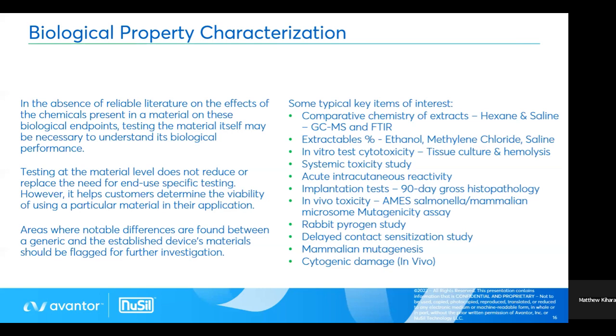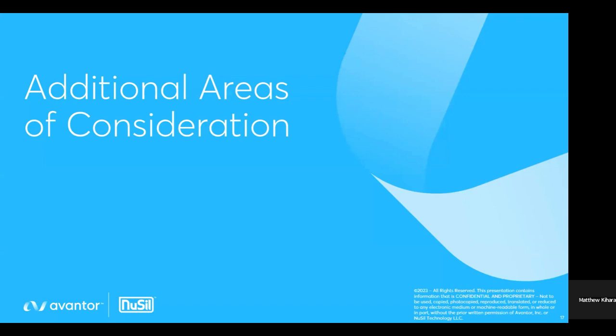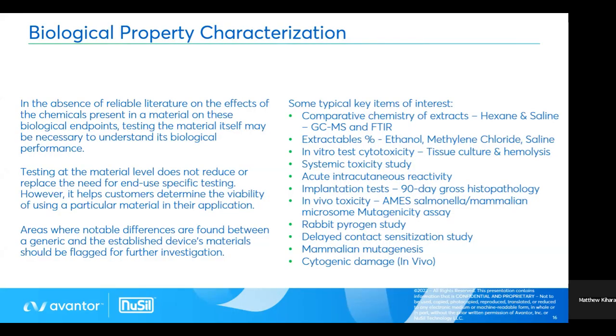Typical key items of interest for biological property characterization are percent extractables in ethanol, methylene chloride, and saline, comparative chemistry of these extractables again in hexane and saline using GCMS and FTIR, in vitro testing for cytotoxicity, a study for systemic toxicity, a study for acute intracutaneous reactivity, 90-day implantation test, in vivo toxicity, a rabbit pyrogen study, delayed contact sensitization study, and in vivo cytogenic damage. Multiple ASTM test methods as standards and USP standards exist to cover these characterizations, either generically or for specific end uses. Next slide, please.